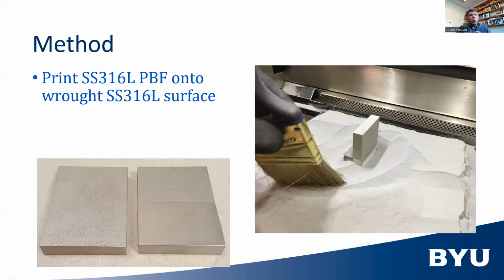So for our method, we took stainless steel 316L in a wrought block and put it inside a powder bed machine, an EOS. And from there, we built additional material, also out of the same stainless steel 316L, on top of it. So in the picture on the left, you can see one block is completely additively manufactured. And then the one on the right is half the original wrought material and then half the powder bed fusion material. You can see that there's a slight difference in the surface finish, but it makes a very good solid product.